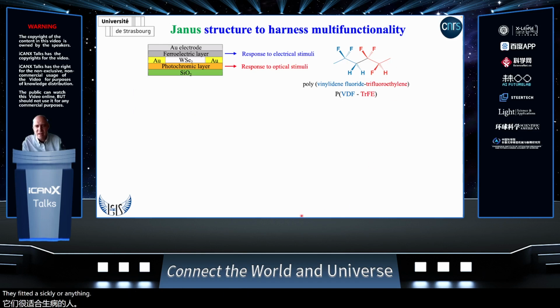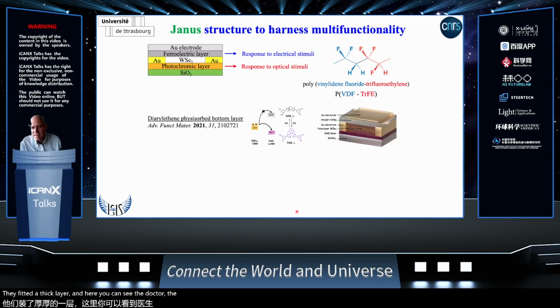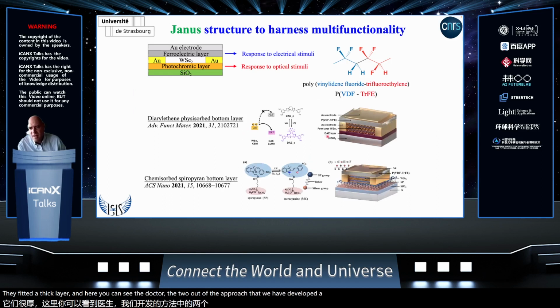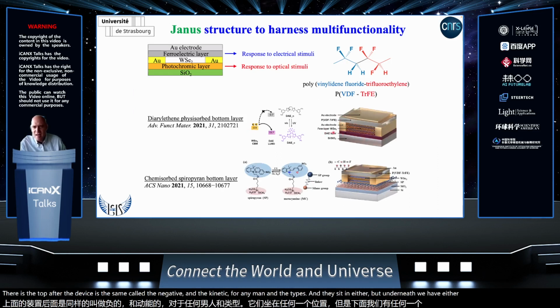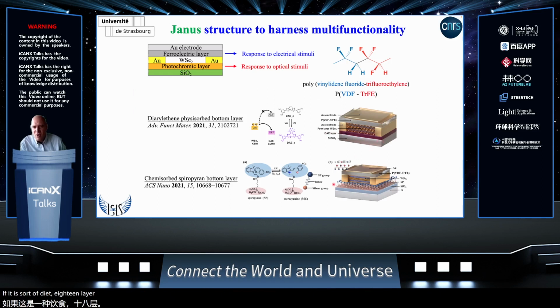And here you can see that two approaches have been developed. The top part of the device is the same: gold electrode, the ferroelectric polymer and the tungsten diselenide. Underneath we have either a physisorbed diarylethene layer or a chemisorbed layer of a spiropyran. Indeed, the spiropyran has been synthesized with a silane unit, and the silane unit can chemisorb only on silicon dioxide. Now, because of time, I will focus only on the diarylethene approach.